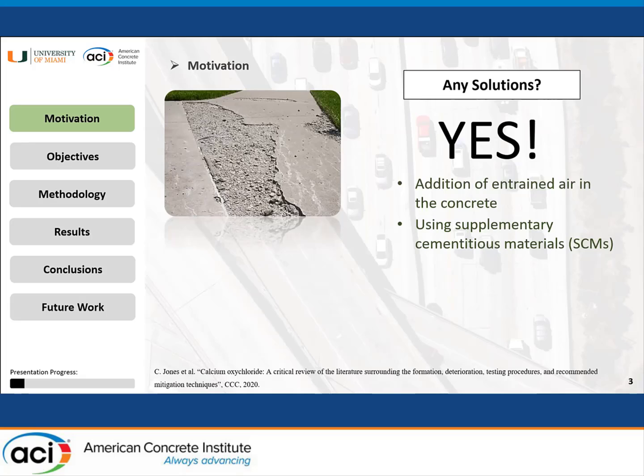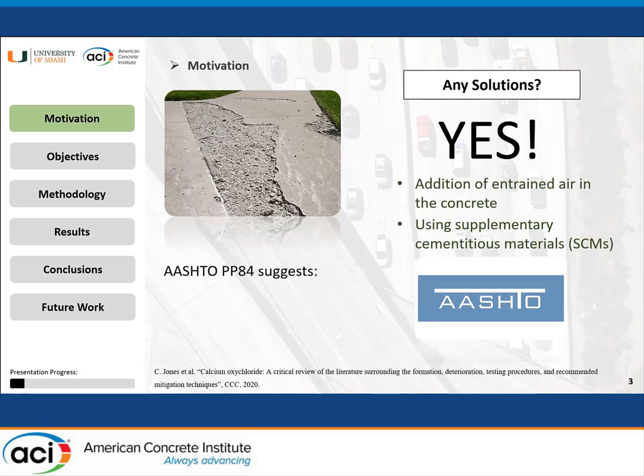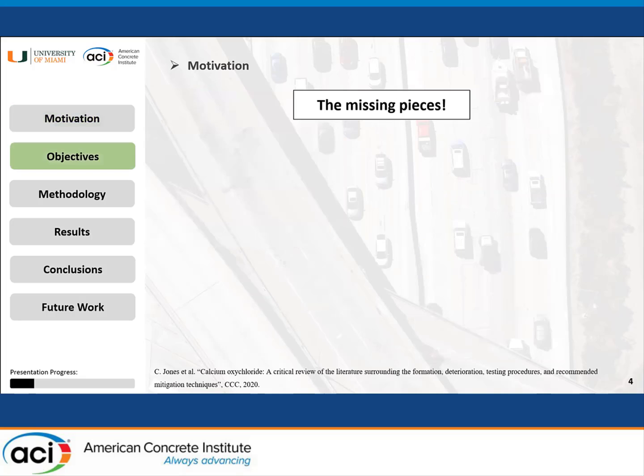How is this going to help? The theory is that by replacing a portion of the Portland cement, we are going to reduce the amount of calcium hydroxide formation, which is also going to result in less calcium oxychloride formation. This is going to help prevent the formation of that expansive byproduct. So AASHTO PP84 suggests that you can replace 35% of your Portland cement with SCMs to reduce this type of phenomenon. In addition to that, you can control your calcium oxychloride to less than 15 grams per 100 grams of your cement paste.